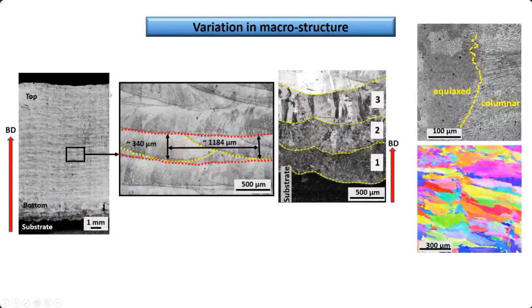We created a montage by stitching hundreds of images, and you can see that the layered structure is very much evident. If we look closely, we can see the hatch spacing and the layer thickness very clearly. We have characterized and quantified that, and seen that in each layer the microstructure is changing distinctly, even at not so high magnification optical microstructure itself.